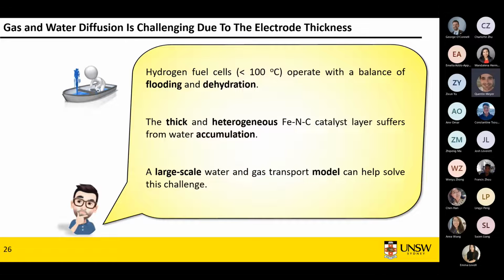Now I'm going to talk about something else altogether. So now, basically, how to look at water and gas diffusion on a large scale. So fuel cells operate below 100 degrees. As a result, they form a lot of water. And this water is a good thing, it could conduct protons, but it's a bad thing at the same time because it will cause dehydration and flooding. You don't want flooding. If you have flooding, you can't reach your active sites. You're done. So in PGM-free catalyst, because we have such a thick electrode, flooding is even more of a problem because you can have catalyst layer flooding in itself, just cracks in the catalyst layer, and just a lot of water forming inside these cracks.